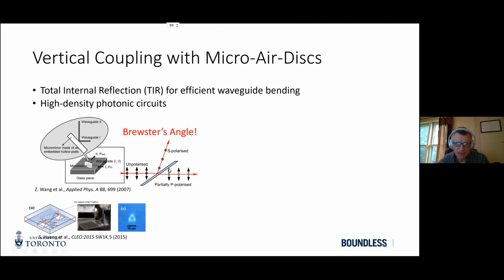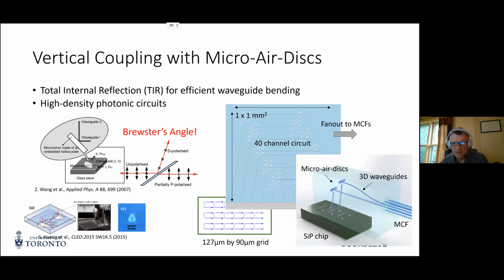So by chemically etching out a channel, we can make a reflector. So here's a cartoon showing a design of horizontal waveguides. So this, in fact, is a glass panel, which could be thin. We can mount fibers horizontally onto the edges using the ideas as you see down here. And then we build with lasers waveguides horizontally and vertically so we can access the grating coupler in the silicon photonic chip. And we chemically etch out these mirrors.